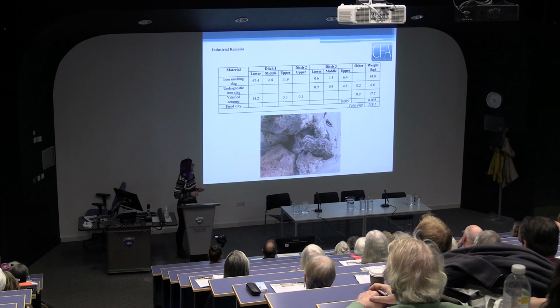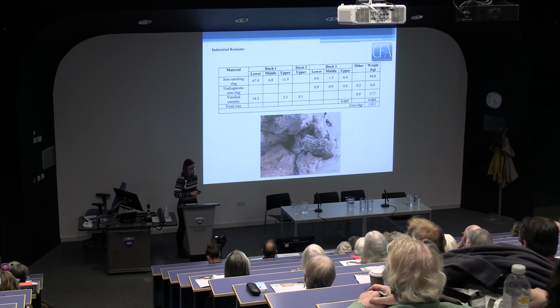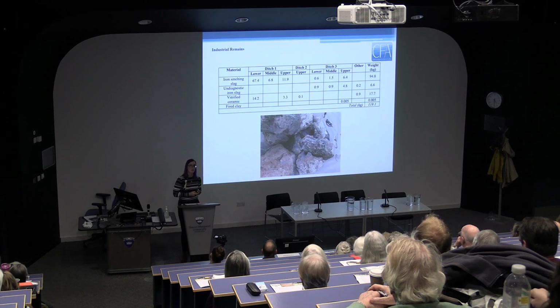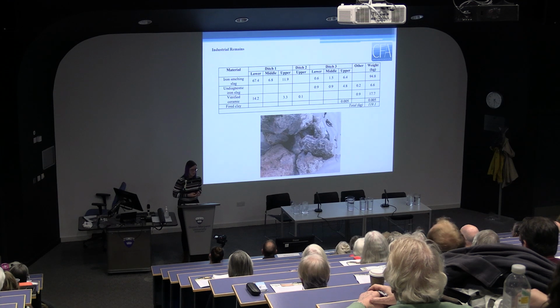Both of these show that smelting activity has to have been nearby, even though we have probably lost the structures to ploughing and the insertion of all the field drains. There's little other evidence for Iron Age ironworking in the Lothians at the moment, so this is a significant find for the region to show that there was large-scale iron production going on in the area.